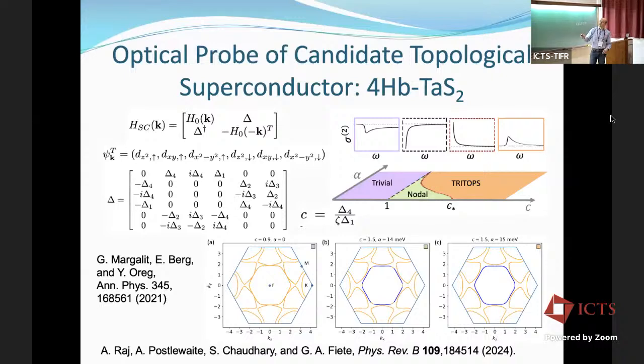And then this is the phase diagram. This axis is a ratio, basically, of the triplet to singlet pairing. And then the vertical axis, alpha, is the spin-orbit coupling that's present in the material. Tuning through these two parameters, you have three phases of the superconductor: a trivial superconductor, a nodal superconductor, and a time reversal invariant topological superconductor, or TRITOPS for short. As a function of these parameters, this is what the band structure looks like. And the sign of the pairing is coded here, with the blue being opposite the orange, so plus 1 or minus 1. You can see that as you move along this axis, you're changing the pairing around the gamma point. So that's the transition from trivial to nodal to topological.